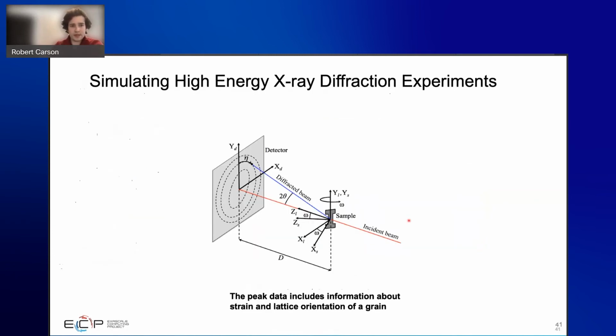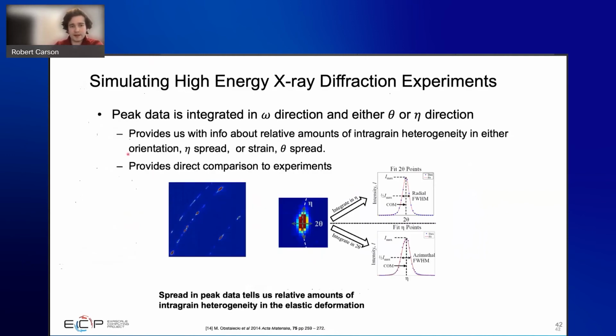Next, I'll just mention that you can also simulate high energy X-ray diffraction experiments. That's pretty cool because these high energy X-ray diffraction experiments are able to get you at the intragrain heterogeneity for either your lattice orientations or your elastic strains for each grain. It can also give you a few other things as well, but it's pretty cool that you can do a direct comparison between the two if you simulate your high energy X-ray diffraction experiments from your crystal plasticity simulations.